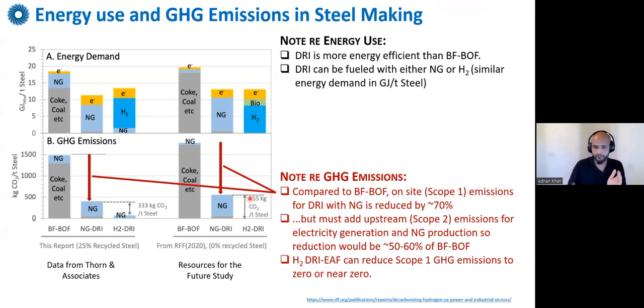60%, right? But what is very clear from the chart here is that the hydrogen DRI route really has the best potential for reducing your scope 1 GHG emissions. Again, the entire process only makes sense when you have very, very low carbon hydrogen available to you at scale to do this process. But another key thing I'd like to highlight here, and which is really the key message from this slide, the key takeaway message is this.